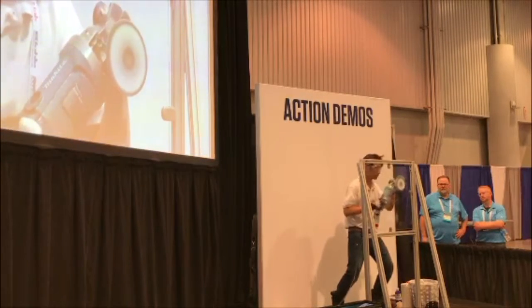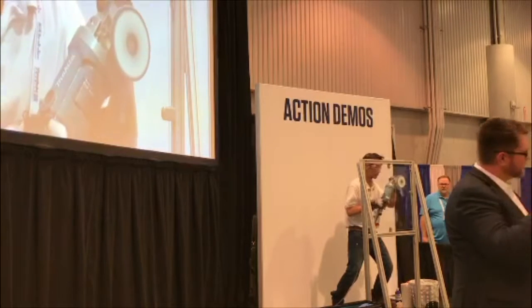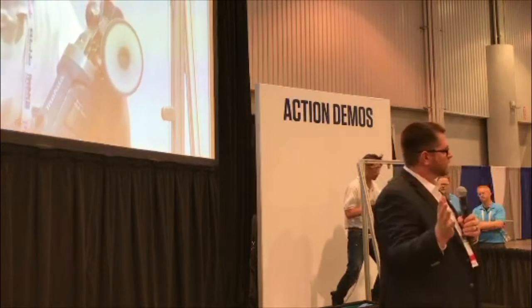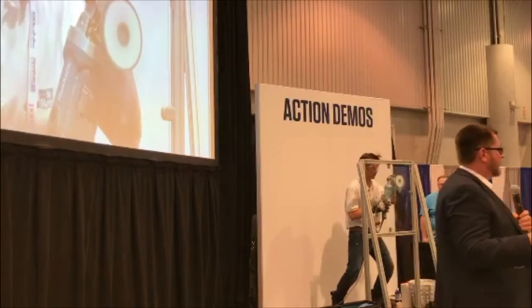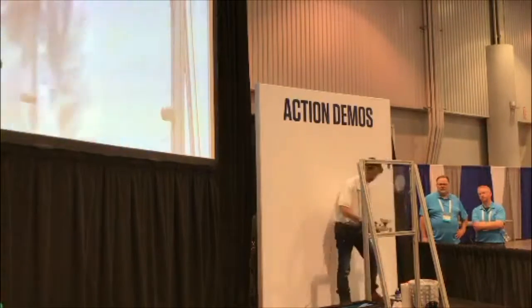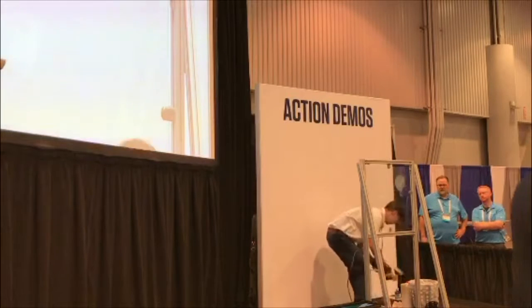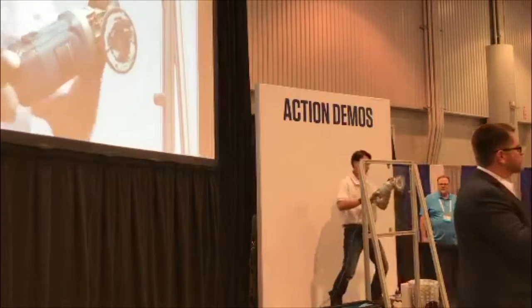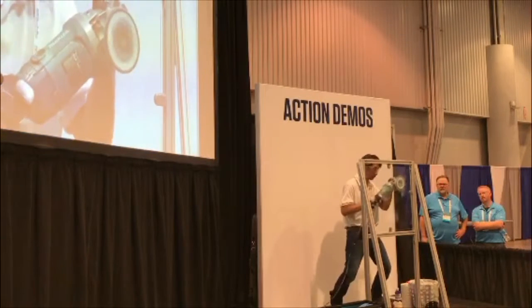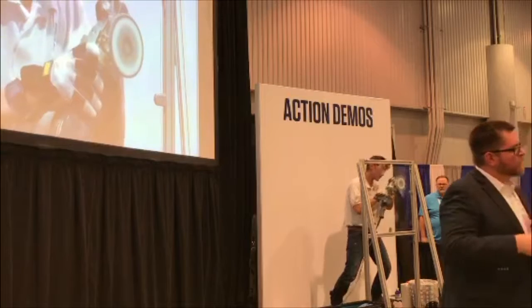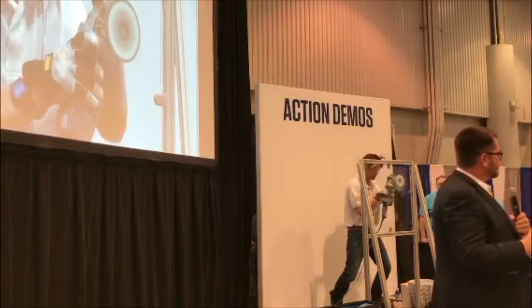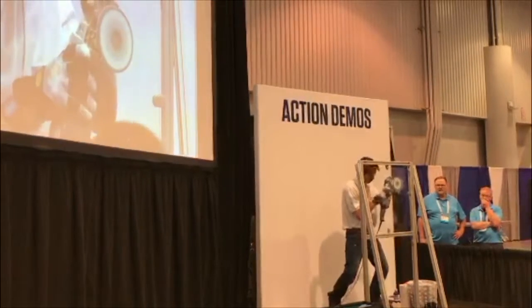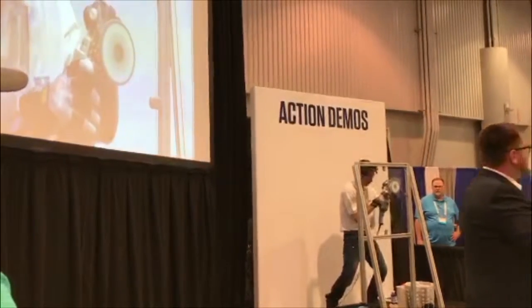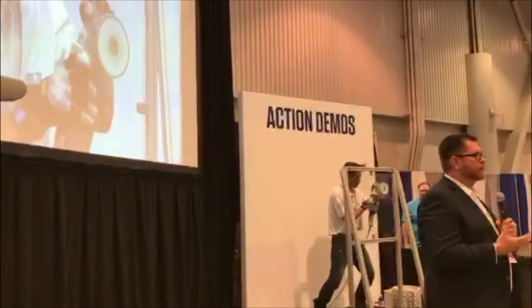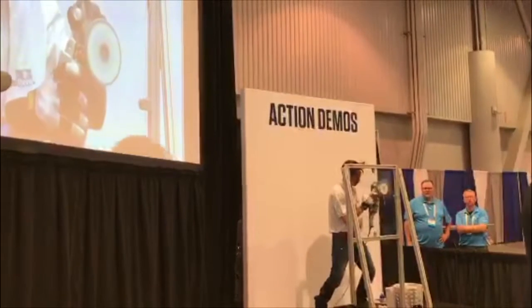Now there are a couple of things that you're looking at right now and you might be wondering, okay, first of all, we did not invent scratch removal. People have been trying to remove scratches from glass as long as people have been using glass as a building material. But what we did invent and what we did pioneer is dry grinding on glass. Anytime you use water or a coolant as a lubricant when you're doing scratch removal, you run the risk of creating optic distortion. And really what you're going to do is create a lens in the surface of the glass. There's nothing you can do to prevent that, because the reality is water is a non-compressible medium,